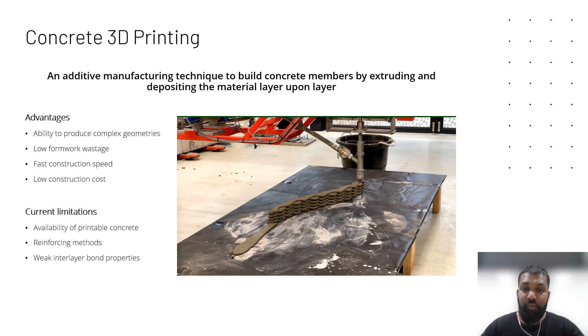However, there are some limitations in the development of this technique. As we know, the area is very new so we have only a limited amount of concrete mixtures, and they generally use high binder content and less coarse aggregates. We are still progressing on how to install reinforcement to these concrete members, and when we print layer by layer, an interlayer zone is formed between the layers which is generally weaker than the rest of the concrete.